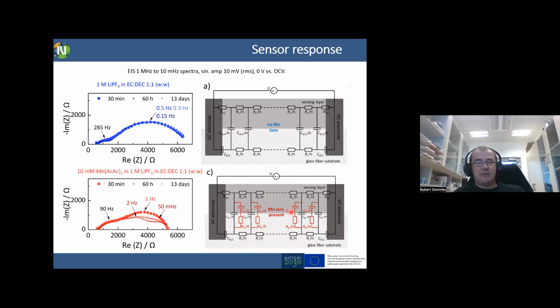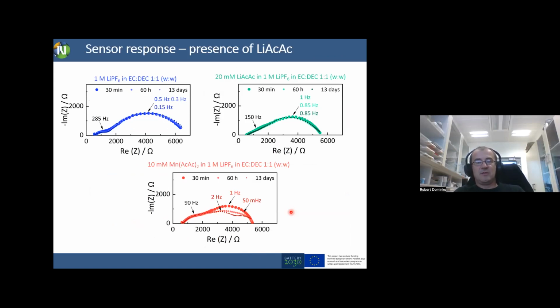So one might already have the question, how about other ions? Is this a property of acetylacetonate, or is this really a property of the manganese? Here, again, is without any additional salt inside the electrolyte. If we put lithium acetylacetonate, you see there is no difference, so impedance spectra are repeatable. If we put manganese, that's what I showed, and I don't have results here for nickel, but nickel is also sensitive, though maybe less sensitive compared to manganese, with this imprinted polymer that I showed. Also, when you are cycling an NMC electrode, we can see that there is some shift in this mid-frequency range of the impedance spectra.